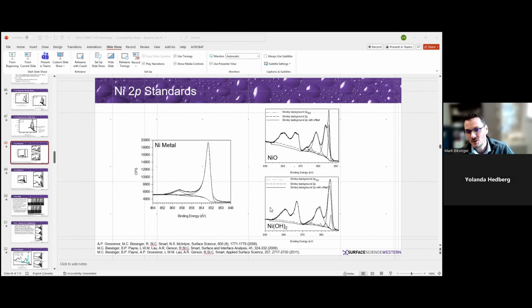And this offset amount changes depending on how much this background goes up or down. This is a problem where the math for the Shirley background calculation can't handle all that's going on here. And so it's one of those areas where the Shirley background isn't great, isn't perfect. So you have to do some modifications in order to make the curve fitting work correctly. But I talk about this in the paper and how to make this work. It's an iterative process. It does work pretty reasonably once you do it that way.